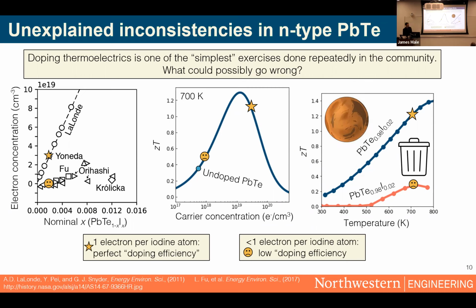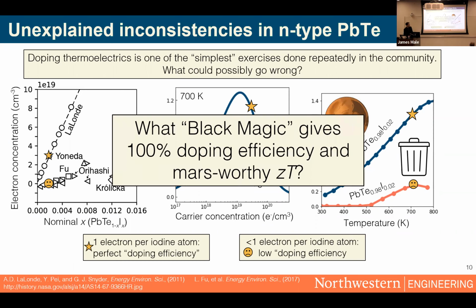What that means in terms of performance is a sample with an identical composition but high doping efficiency can actually achieve a very high ZT, whereas the low doping efficiency sample is essentially garbage. And in fact, these high doping efficiency samples are what we believe is on the Mars rovers, whereas these low doping efficiency samples are garbage. So one key point here is these two authors on paper are making the exact same thing, but obviously the performance is drastically different. So the question I want to answer is, what is the special sauce that gives you the good material and what gives you garbage?